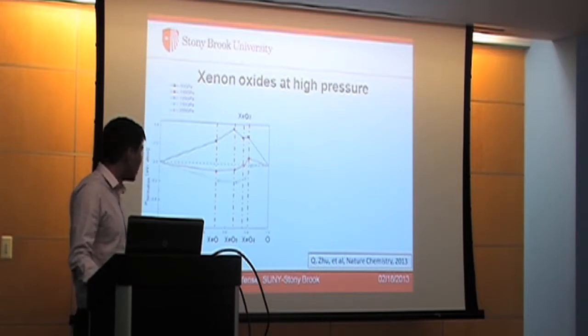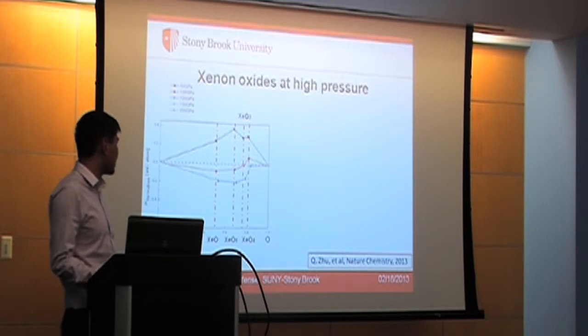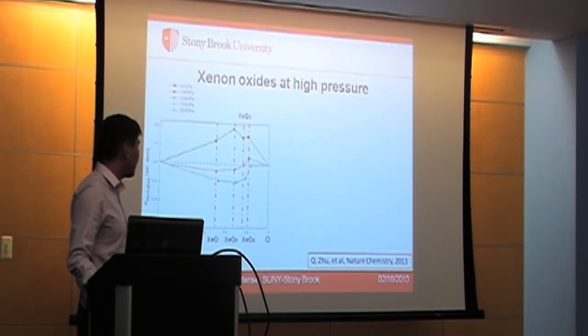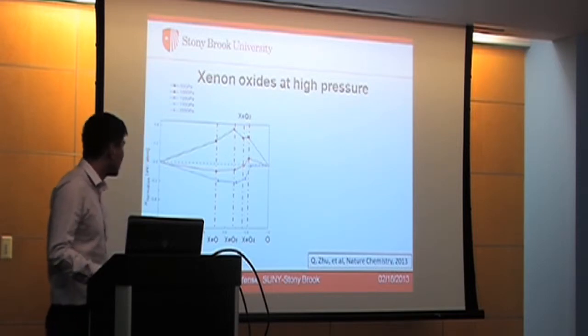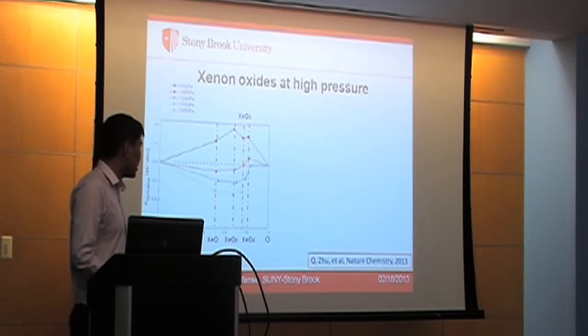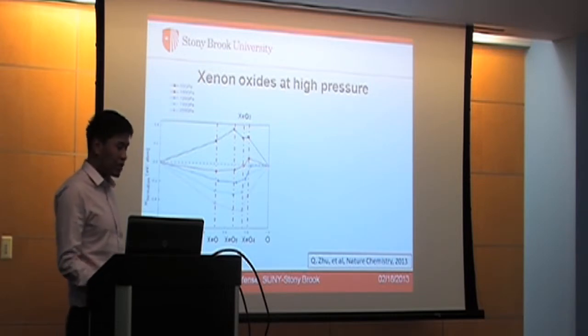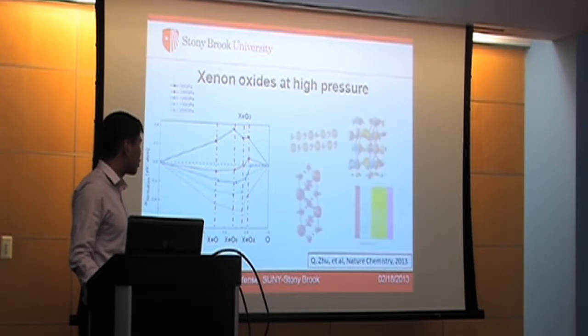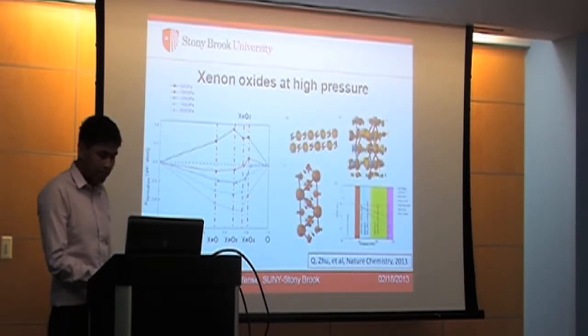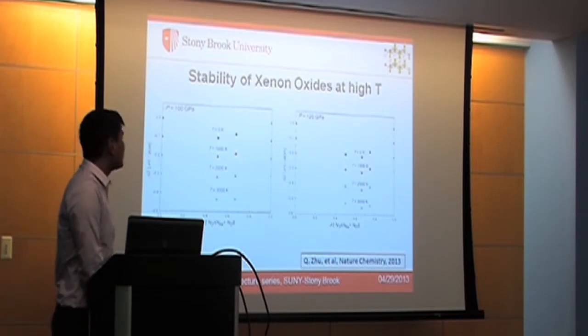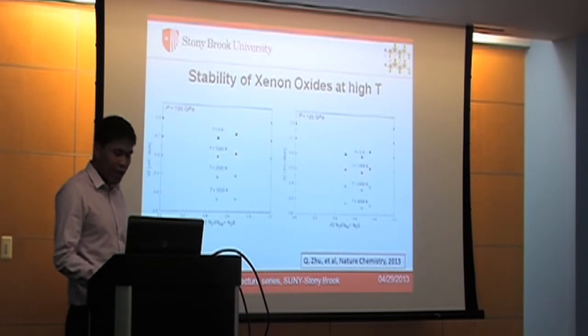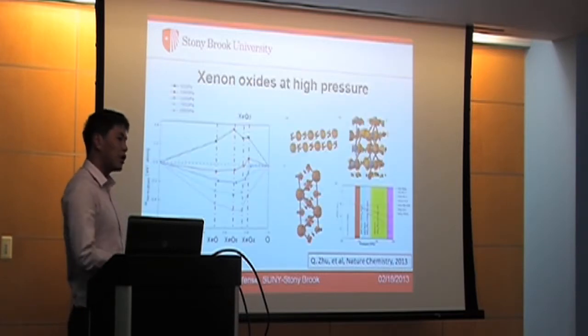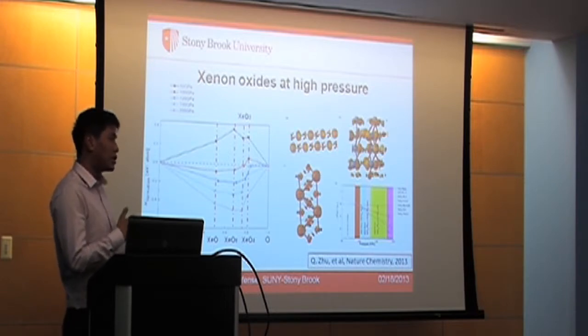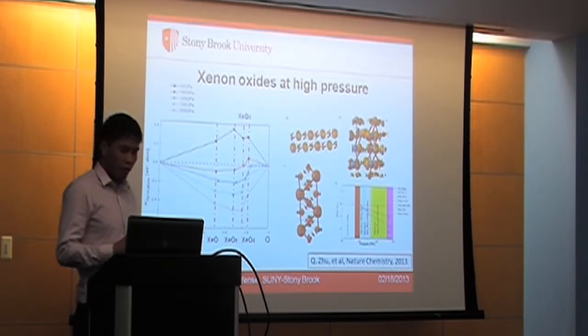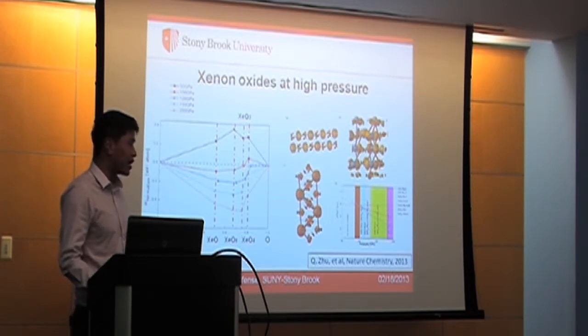And then if we increase the pressure further, we can clearly find the trend that the stability of the compounds can be significantly enhanced by pressure. So with this, we can get a full picture about this system, the stable compositions, and the corresponding stable crystal structures. Some people might argue that all of these calculations are done at 0 Kelvin. But imagine that in the Earth's mantle condition, it must be at very high temperatures. So we should include the effects of temperature.